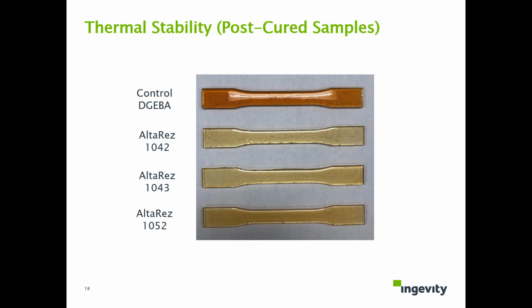Another interesting thing we found is color stability at high temperature. Like post-cure, when this epoxy sits at 150 C for 3 hours, the control sample has a much darker color than our AltaRez epoxy at the same temperature. So this may suggest that AltaRez epoxy may have good UV resistance, but we don't have data, we don't have tests so far. We're going to do the test. It will be an interesting area to look at.